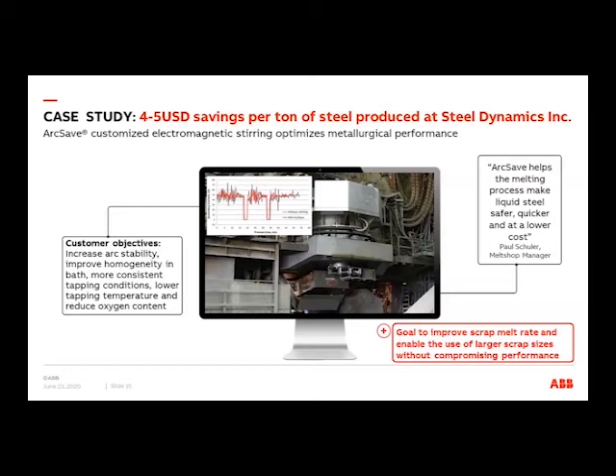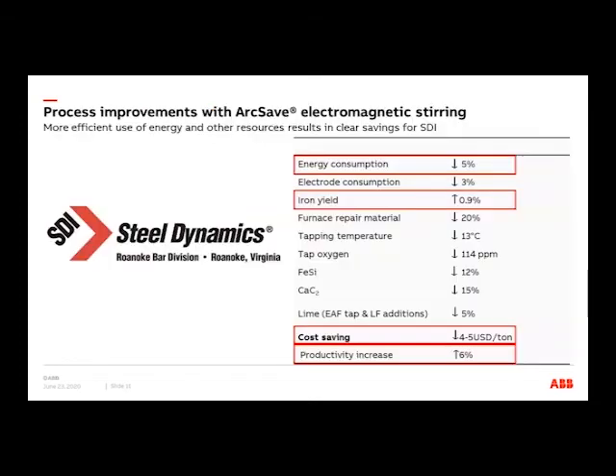"ArcSave helps the melting process make liquid steel safer, quicker, and at a lower cost." Also here on the next slide, you see a summary of the benefits we got out from the performance test. Some is highlighted, for example, energy consumption was reduced by 5%, iron yield increased by 0.9%, which gave a cost savings of the operating cost of $4 to $5 per ton. And also an additional benefit was that productivity was increased by 6%.